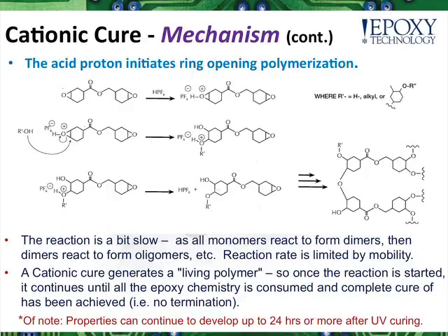That's actually an additional entire monomer. In the third reaction, you can see the acid actually leaving and being replaced or substituted with that new monomer, that second monomer. You can see in this the acid is fully regenerated, so this is a truly catalytic reaction. Now, this process will continue forward until completion, and that will create a large polymer network or a polymerization.